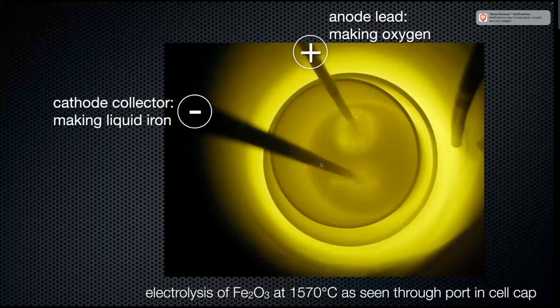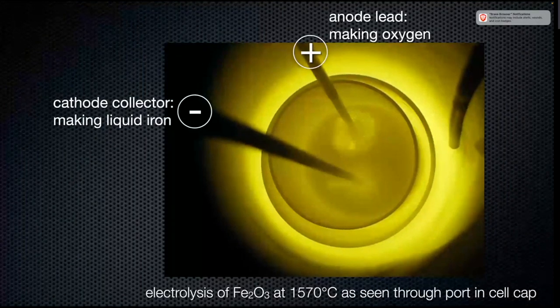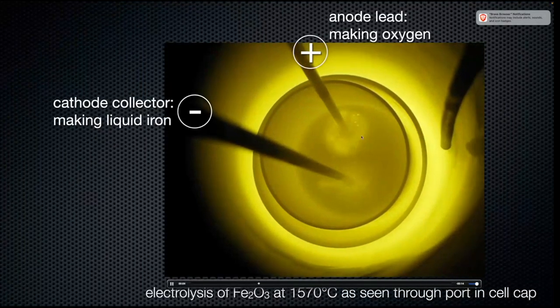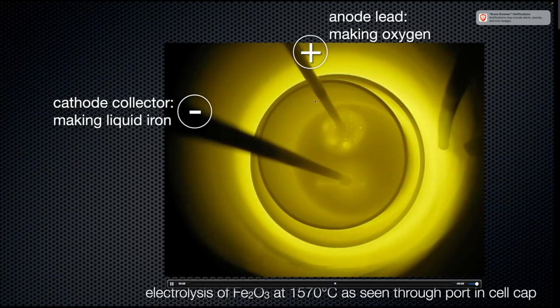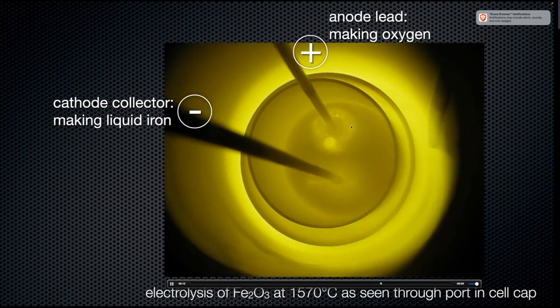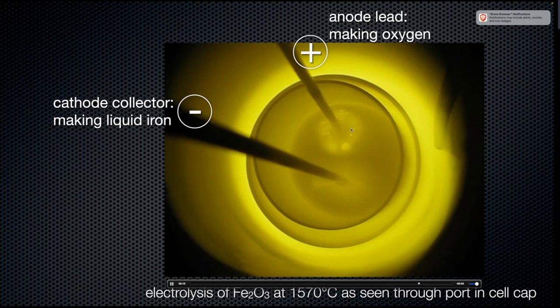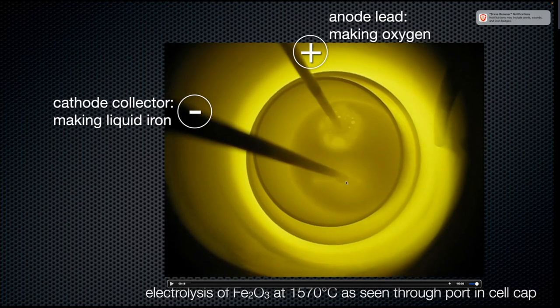And so when this is operating, the passage of electric current generates oxygen here on the anode, and here it's generating liquid iron, which is going to fall off and drip to the bottom of the cell. So let's see what happens. So you can see the oxygen bubbling here. You can see this, it's pretty viscous, but yet we're able to get the oxygen to release. And then here we're making the iron, which is falling to the bottom of the cell.